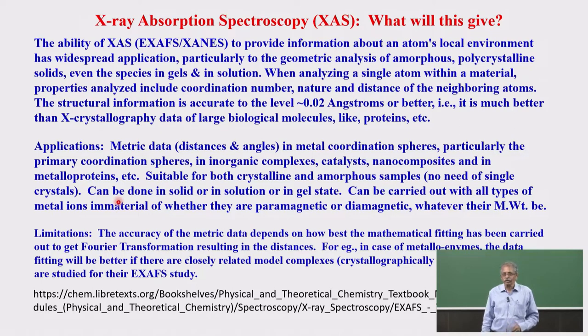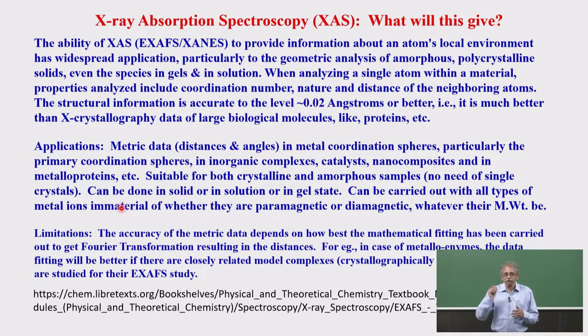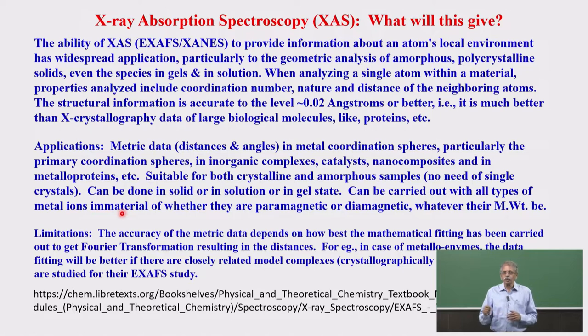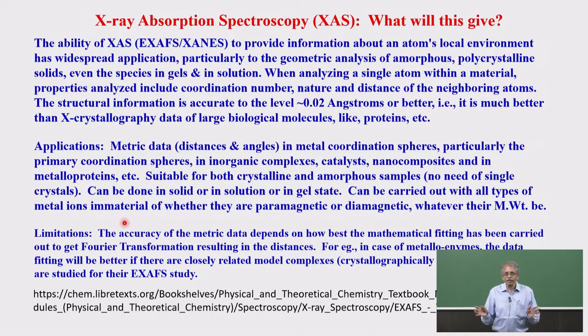There is a great advantage over X-ray crystallography. For small inorganic compounds, single crystal X-ray diffraction is extremely accurate — standard deviation of 0.001–0.002 Å. But for huge biomolecules, the accuracy drops to 0.1–0.3 Å depending on resolution. Whereas EXAFS and XANES, even for metalloproteins, metalloenzymes, and huge biomolecules, require no single crystal in any form — solution, polycrystalline, or amorphous — and still achieve 0.01–0.02 Å accuracy.